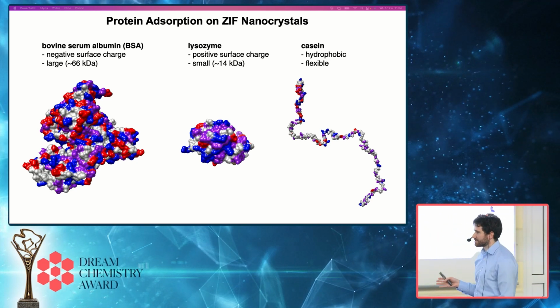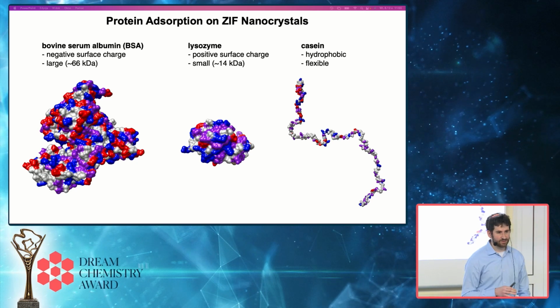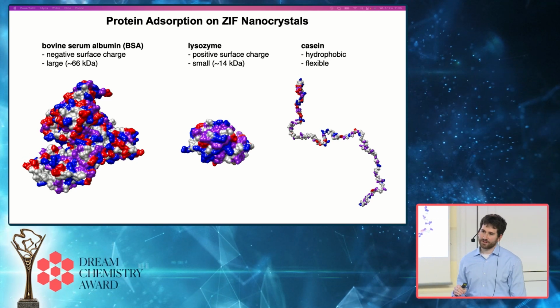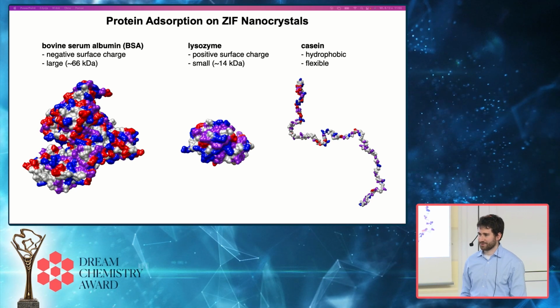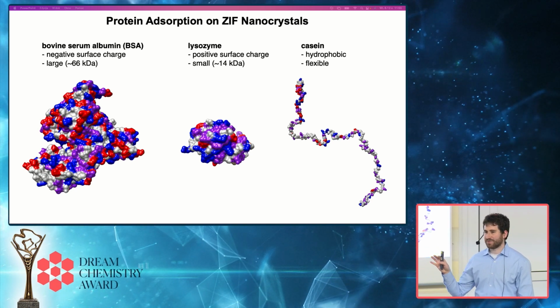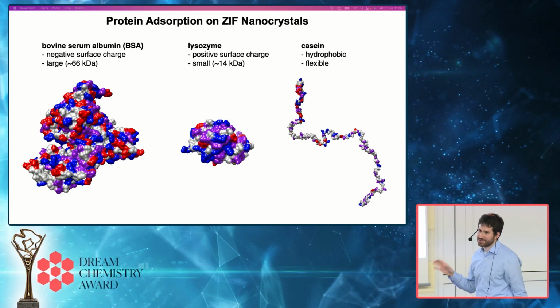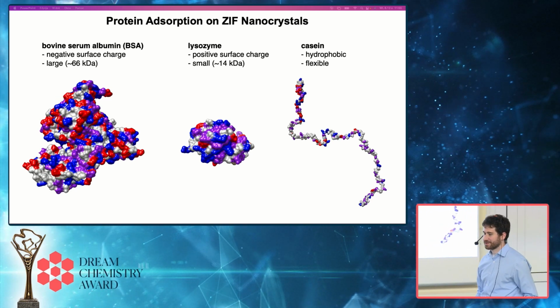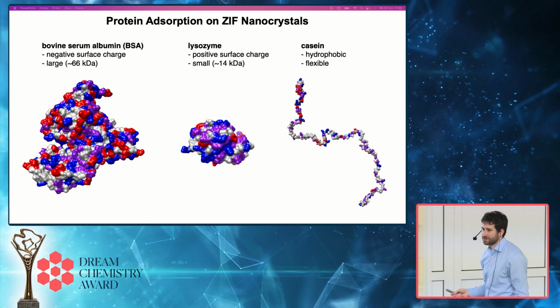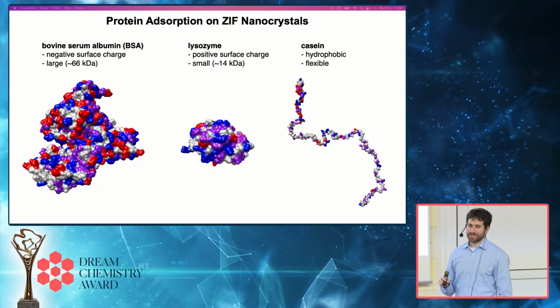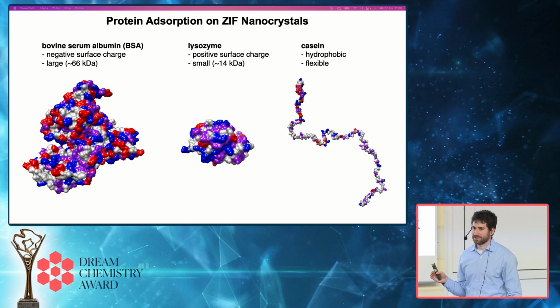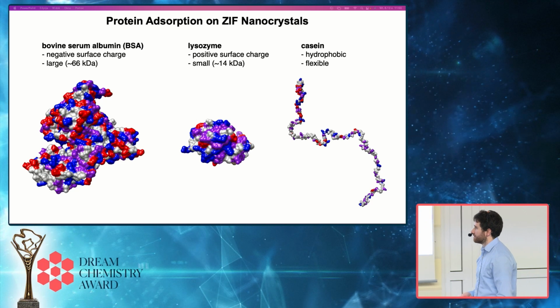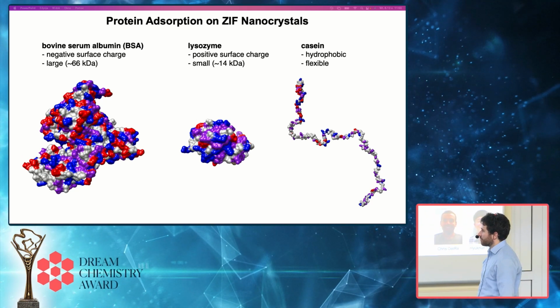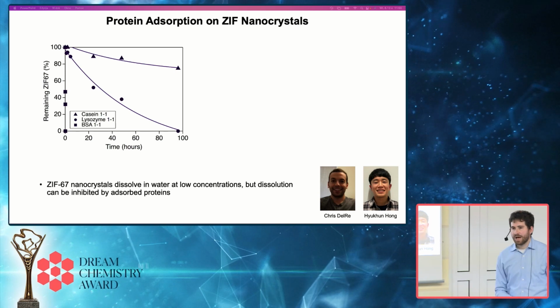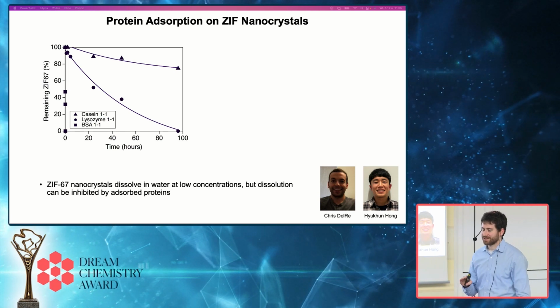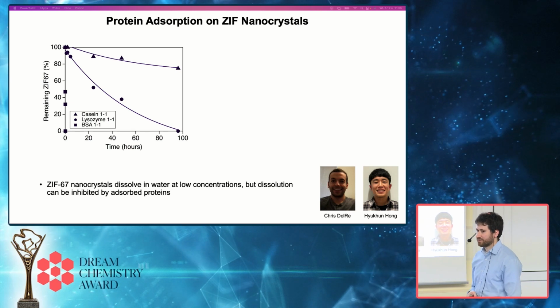So this particular class of metal organic frameworks, these ZIF metal organic frameworks, are actually not that stable in water, and at low concentrations they will dissolve. So this gets back to some of Carl's dynamic metal ligand bond arguments. At low concentrations, you shift the equilibrium toward having water bind the metal center rather than your bridging organic ligand. A lot of these will dissolve in water at low concentrations over time, which can be useful for some biomedical applications where you need to be concerned with how particles will be cleared, and is less useful for other applications. But more fundamentally, we're just curious to start understanding why different proteins induce very different changes in the actual stability of a lot of these MOF particles.